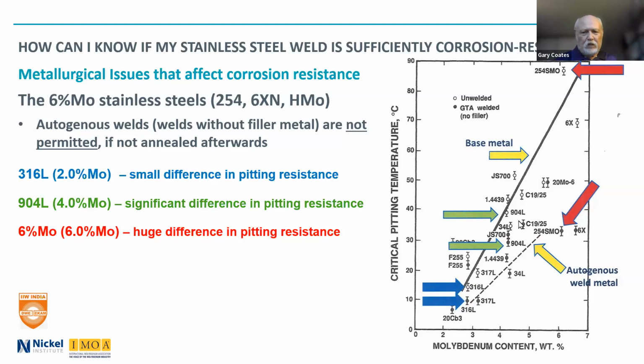When you get into the 904L with 4% moly, you are seeing a difference, and therefore if you know pitting is a distinct possibility, you shouldn't weld 904L with the matching filler metal or do an autogenous weld either. And when you get to the 6 moly alloys, there's a huge difference. So you should never weld 6 moly alloys without filler metal unless they're being annealed afterwards.